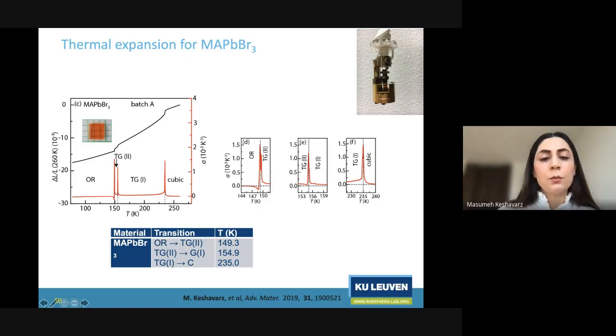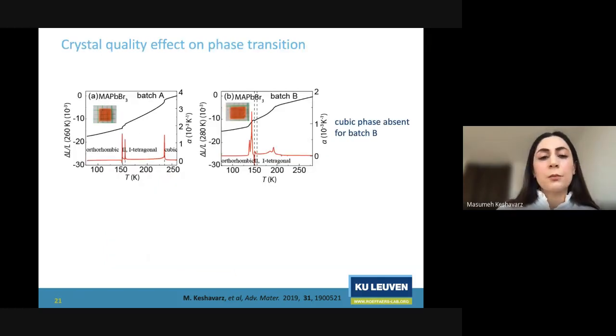So here you see a zoom into the position of the phase transition temperatures. It is very accurately identifying the transition temperatures. Now we took two different batches of the material, single crystals of methylammonium lead bromide. Batch A is freshly synthesized, and batch B is 1 year old, just kept under ambient conditions on the table. So we wanted to know how this degradation of the material affects the structural properties.